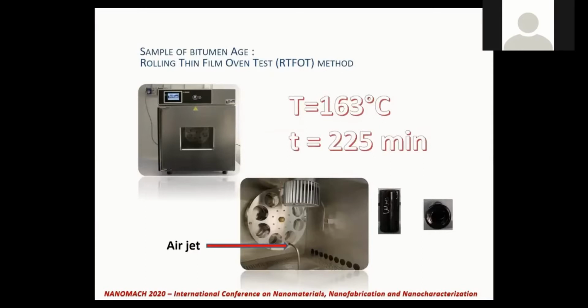In order to study the effects of aging in the laboratory, the method known as rolling thin film oven test was adopted to simulate the aging of asphalt binders. The apparatus consists essentially of an internal double-wall furnace in which the hot air circulates, conveyed by an internal fan, at the test temperature of 163 degrees. The test consists in subjecting a thin layer of bitumen to a hot air jet for 225 minutes.